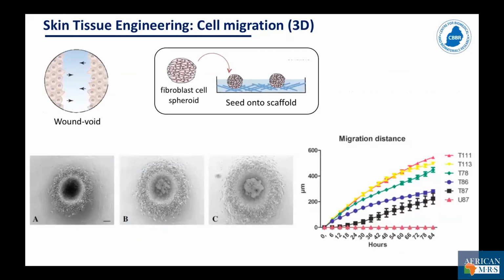And we can also use spheroids to have an indication about the cell migration on scaffolds. We can use, for example, fibroblast spheroids, seed them onto scaffolds, and monitor the migration of cells onto the scaffolds. And we can plot, for example, a graph of the migration distance with time. And this can give you an indication about how much the scaffold is promoting cell migration.